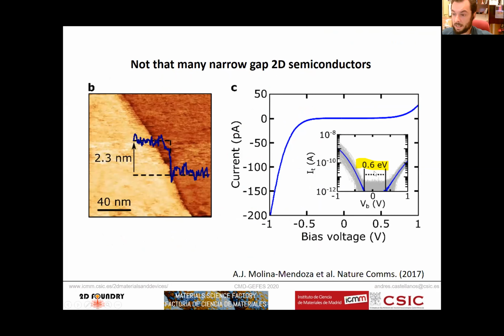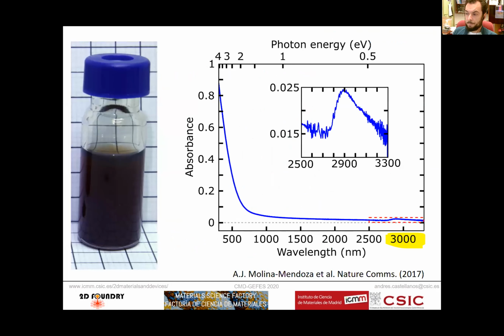We have seen in scanning spectroscopy measurements that this is indeed a quite narrow bandgap. And we have also done some liquid phase exfoliation in collaboration with Emilio Perez's group, and we have done UV-Vis absorption. We have seen that the material has non-negligible absorbance up to 3,000 nanometers, 3 microns, so well in the infrared part of the spectrum. And we even see this little peak here that we believe is an exciton resonance in our system. All right.